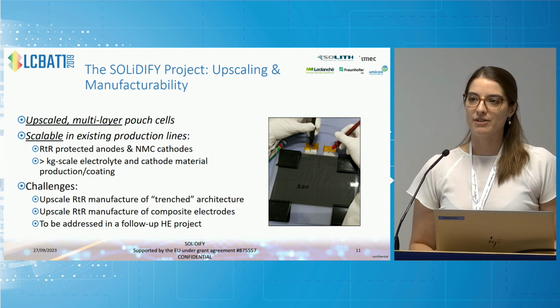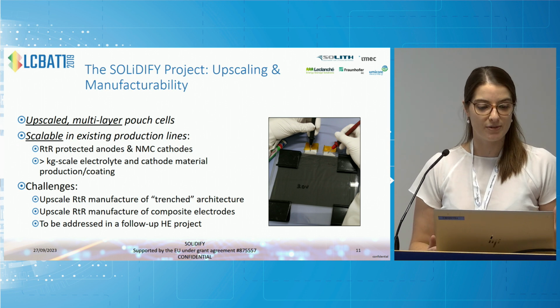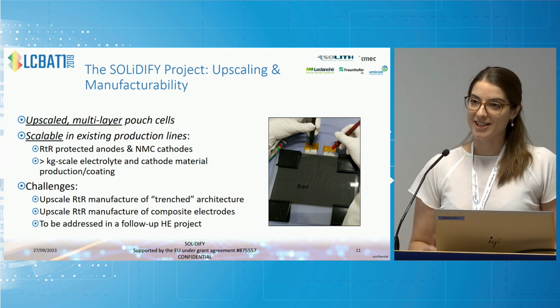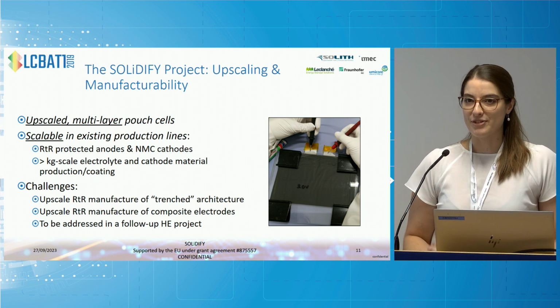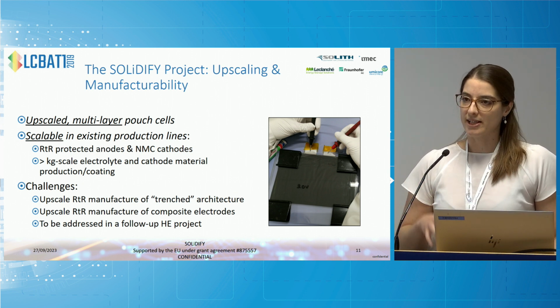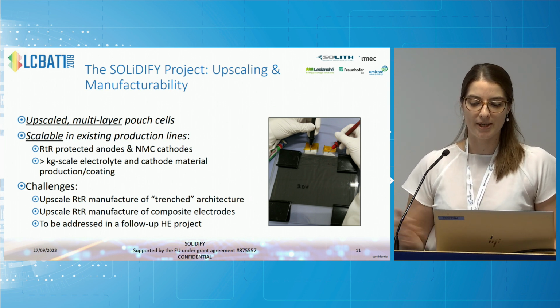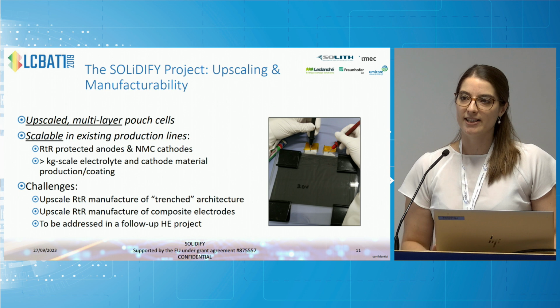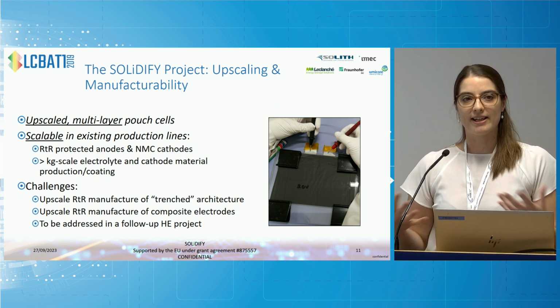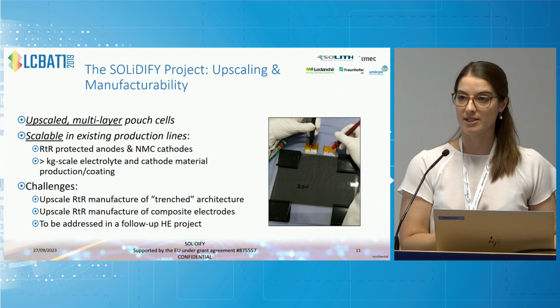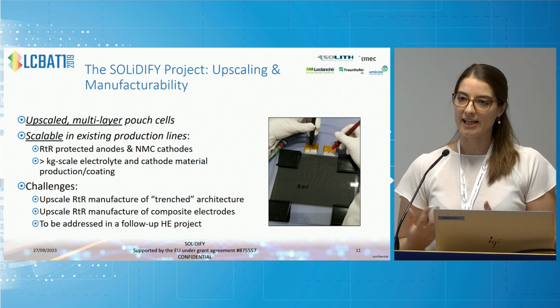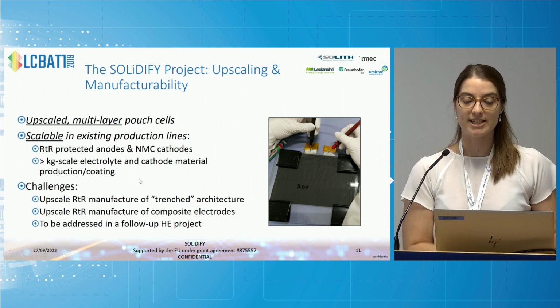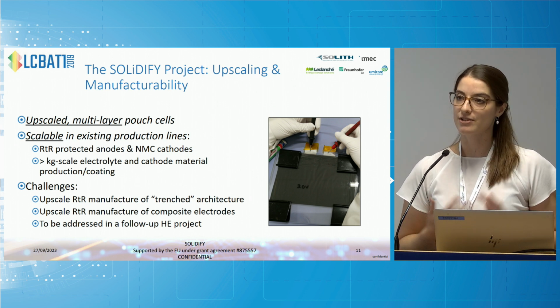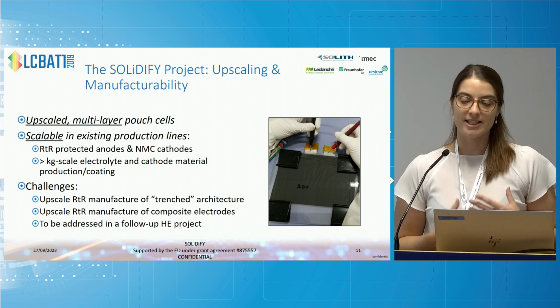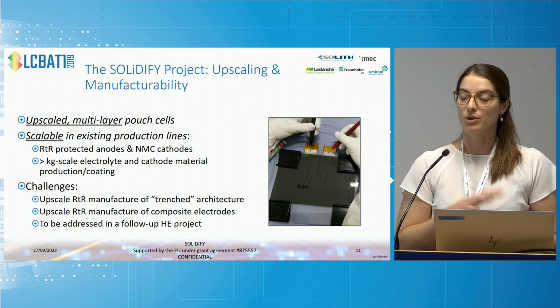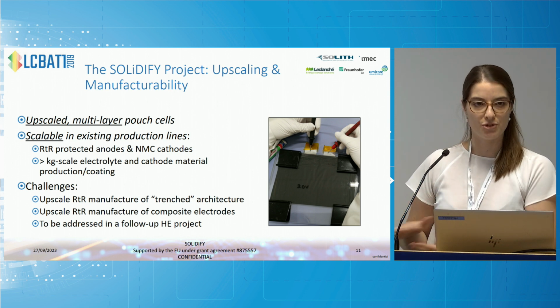And in terms of upscaling and manufacturability, which is really a core focus of this project, we have made multi-layer pouch cells, not performing, of course, at the 450 watt-hours per litre. When we move from, say, coin cell, small pouch cells to much larger pouch cells, so this, for example, is a 10 by 15 centimetre square pouch cell, we then encounter more issues with effectively the materials struggling to deal with the upscaling. And so some aspects are, of course, already scalable in a roll-to-roll process, like the anodes and the cathodes themselves. But we're finding challenges with the manufacturing of like a roll-to-roll process of the composite cathode to the infiltration step of the cathode.